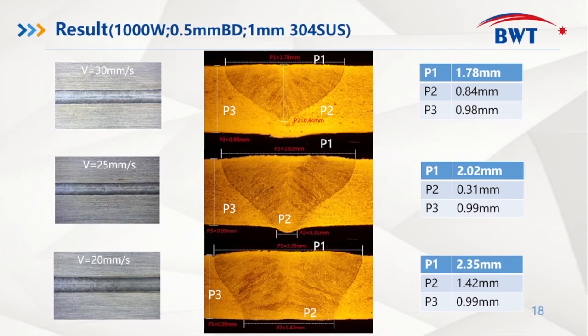1 kW power on 1 mm stainless steel plate. The speed of 25 mm per second can penetrate. When the speed is 20 mm per second, the width of the weld bead on the top surface is 2.35 mm. The bottom width of the weld bead is 1.42 mm.